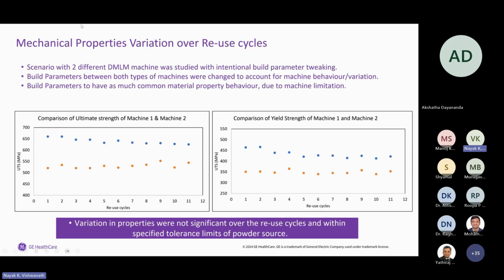And then we studied two different machines, two different scenarios. The conditions were almost similar, machine one and machine two. Blue is machine one, and orange is machine two. We checked, for different reuse cycles, the tensile test coupon UTS and yield. It has to be a typo here, this yield. So this yield and UTS were compared, and if you see, over a period of time the UTS increases slightly from what it was initially, but more or less similar.